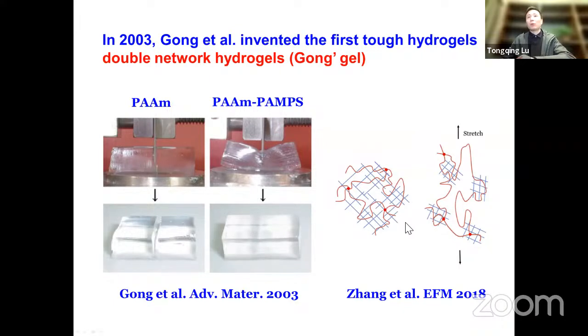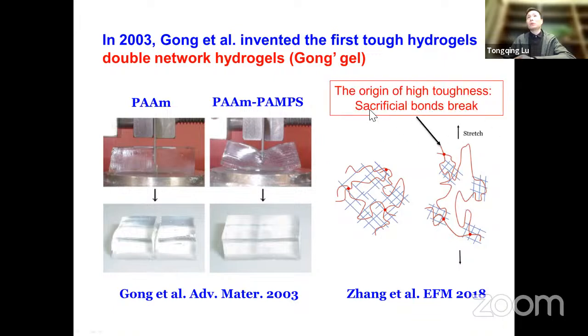Now we have already understood the mechanism of the high strength and high toughness of this kind of double network hydrogel. We believe there are two networks. The red network is a long polymer chain network, and the blue one is a short chain network, a PAMPS network. When you stretch this double network hydrogel, the short network will first break and dissipate energy as heat. That's the origin of the high toughness. We call it sacrificial bonds breaking. This is the first generation of tough hydrogels.